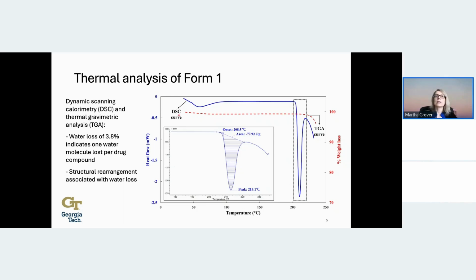And so we start at near ambient condition, and we can see a heat flow around 60 degrees C. So it's kind of a broad feature here, but we can see that there's definitely some sort of feature. And at the same time, we can see a loss in weight. Not hugely large, but it's noticeable. And we were able to quantitate that at 3.8% of the mass. And it turns out that that corresponds to about 1 water molecule per molecule of the drug compound. So this is what we were expecting to see, that we had a monohydrate. So we view this as confirmation that we did have a monohydrate, and that around 60 degrees C, it would lose its water. And then we saw that as we heated it up to 200 degrees C, really no noticeable features, until we got to over 200 degrees C.